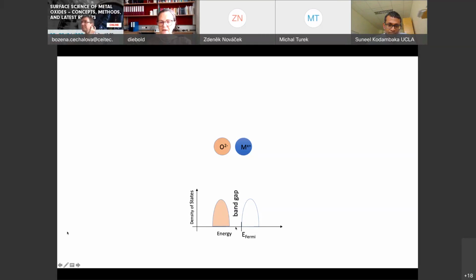And then normally you have a band gap in between. Many of the ones I will talk about have a band gap of about 3 electron volts. So actually the indium oxide and the others have about 3 electron volts band gap. And normally from a formal point of view, in density functional theory, you would put the Fermi level right in the middle of the band gap. But experimentally, we have the Fermi level at the lower edge of the conduction band. And so all the metal oxides essentially have the Fermi level at the lower edge of the conduction band.